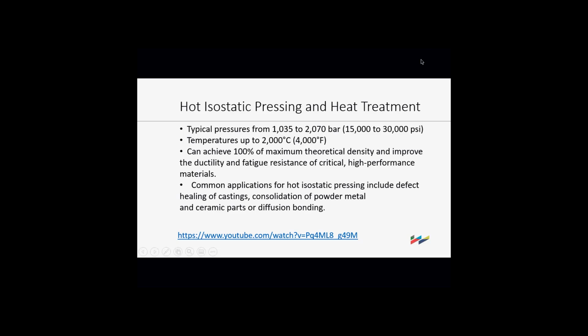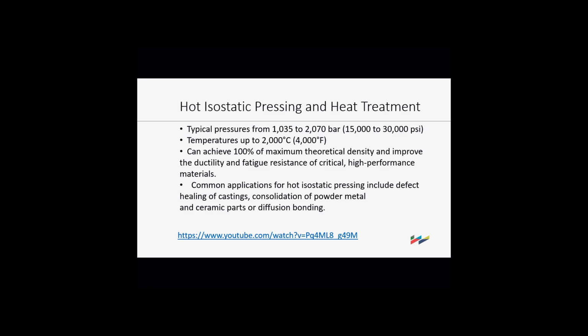Okay. So I talked about hot isostatic pressing, and also traditional heat treatment, which you also use in the devices. The typical pressures they get into are 1,000 to 2,000 bar, or 15,000 to 30,000 psi, with temperatures up to 2,000. What you're doing is taking the temperature just below melting, because you're trying to move atoms around in the device to get rid of the voids inside the device. They basically press them out. So if you have a lot of porosity in your device,